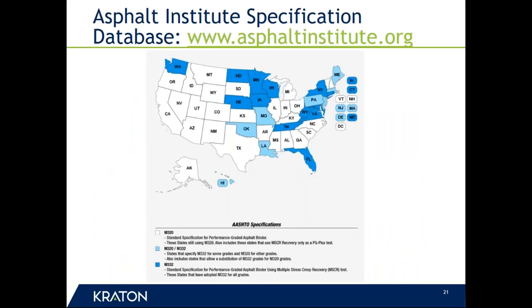I mentioned AASHTO M332 a couple of times, and this slide that comes from the Asphalt Institute website shows the trends as of a couple of months ago. What you see in dark blue here are states that have adopted M332 across the board. What you see in light blue is states that have adopted part of it. And in those cases, it's mostly the MSCR recovery that I mentioned before, as opposed to elastic recovery.